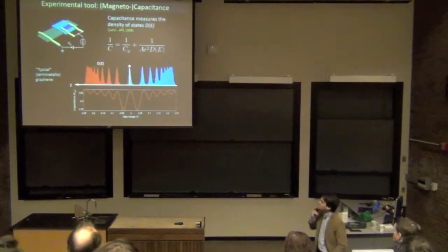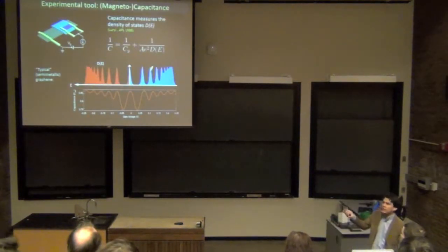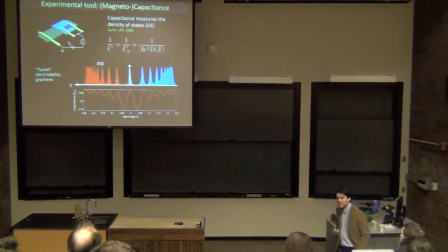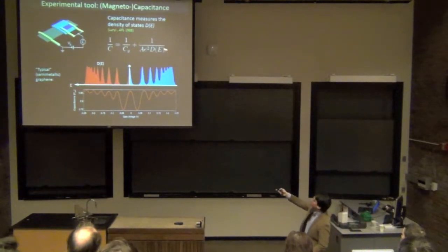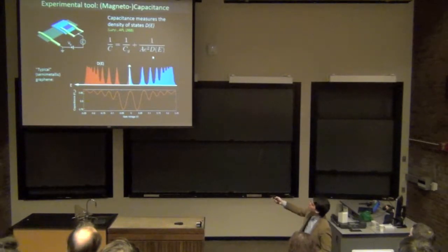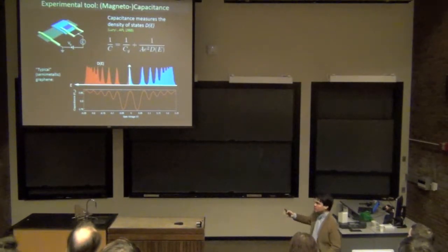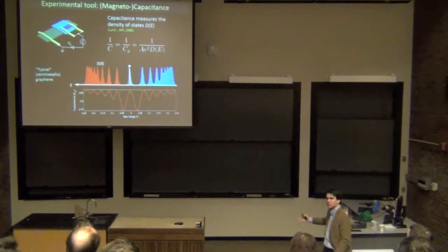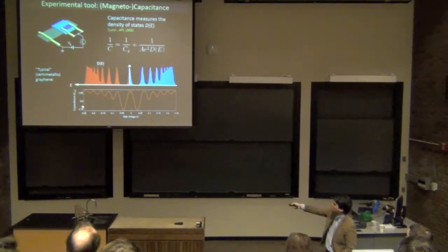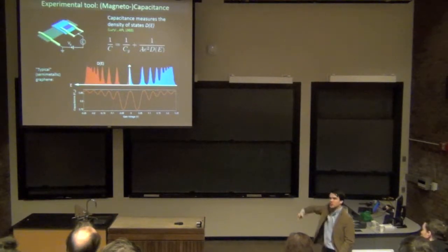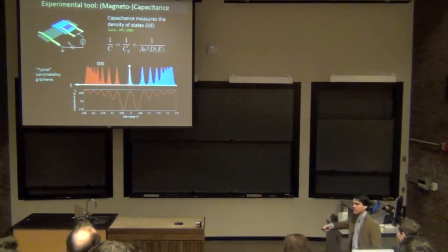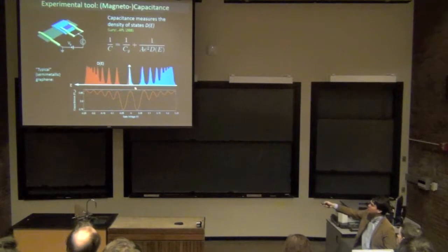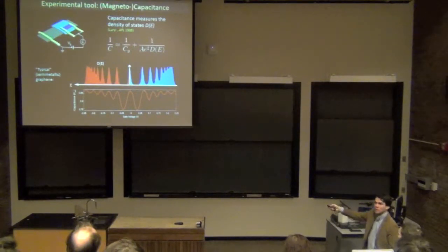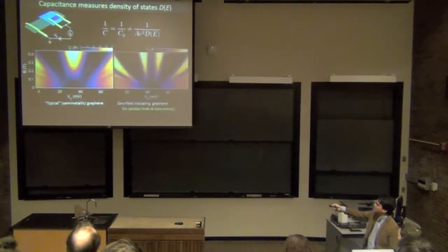So capacitance is a nice way of measuring the thermodynamic density of states, so dN by dμ. Basically it maps compressible and incompressible states to sort of 0 and 1 on capacitance. So it's a nice way of probing transitions between compressible and incompressible states. Gaps in the spectrum show up as dips in the density of states.